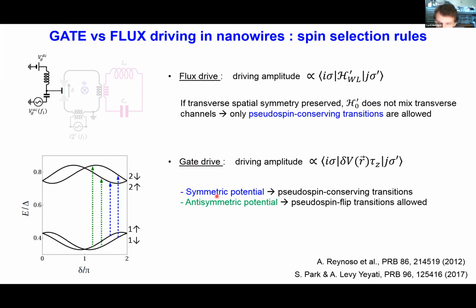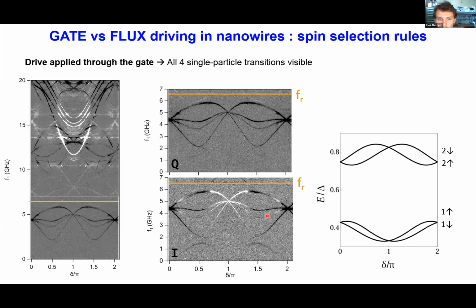the nanowire. So to finish, let me show you a more recent spectrum that we measured, where we also evidence some single quasi-particle transition. And on this quadrature, you can see that we indeed, using a gate drive, see with similar intensity the 4 transitions. However, in the other quadrature of the field, you see that the line intensity has many changes of sign. You go many times from white to black.